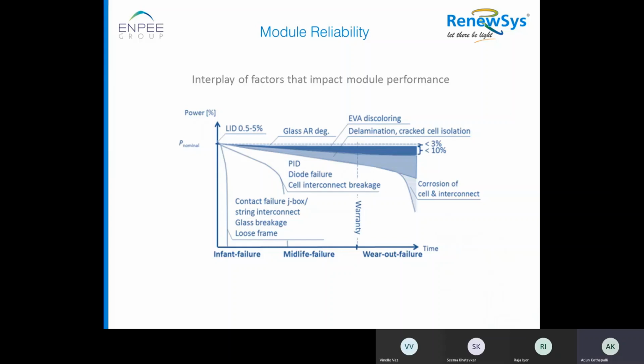We picked up this chart from NREL. Basically, we see that the initial power drop from module reliability is from LID, nothing but light induced degradation. And as per NREL studies, the light induced degradation will be at 0.5 to 5%. And they saw connection failures, j-box failures, string interconnecting failures, glass broken, loose frame. These are the failures they saw.